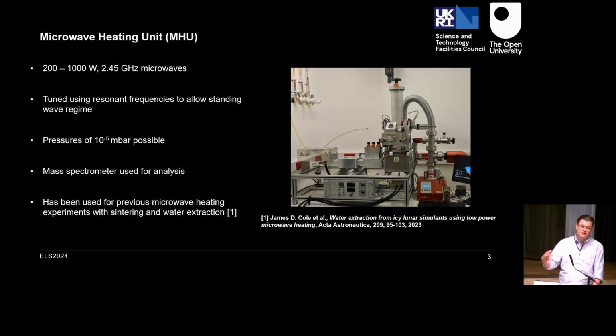At the back end, we've connected it to a vacuum system, which is attached to a mass spectrometer, so we can analyze any of the gases that are released, and we can get down to pressures of roughly 10 to the -5 millibar. As I said, when I inherited this piece of equipment, it was mainly being used for sintering experiments. So I had to work for a while on adjusting it to water extraction, finding the best way of doing that. I performed a few experiments where I adjusted the water content and the simulant type, so Mare and Highland, for different samples, and looked at the water extraction occurring. That's in the first paper mentioned there.